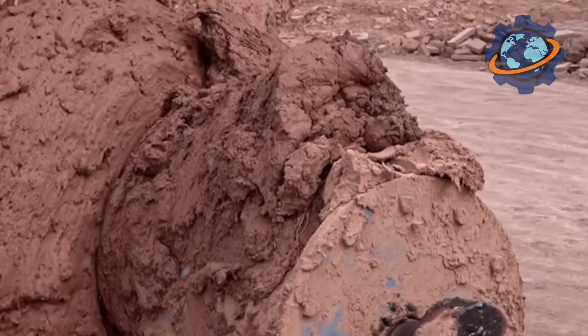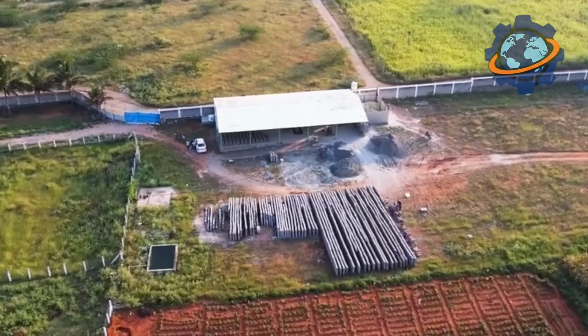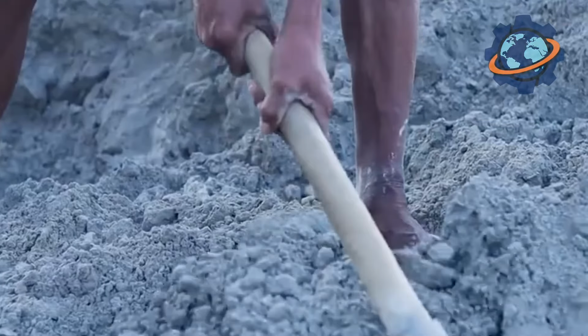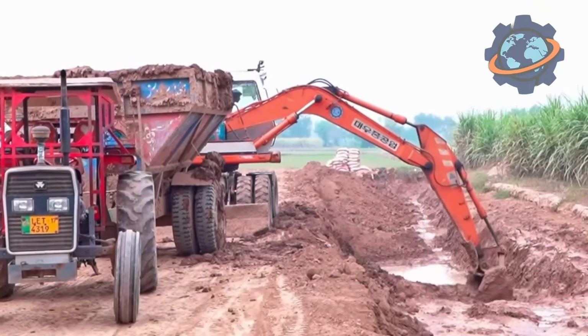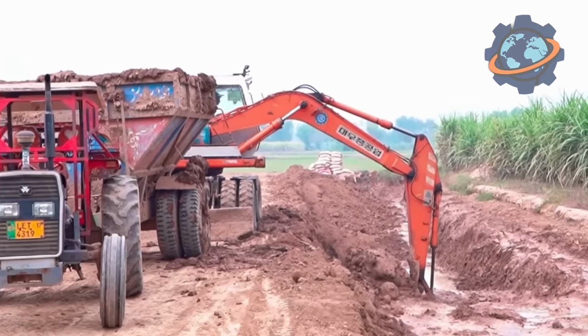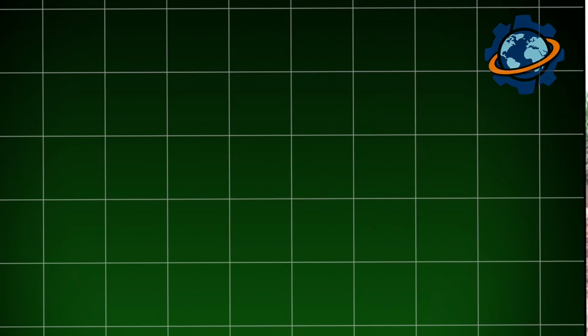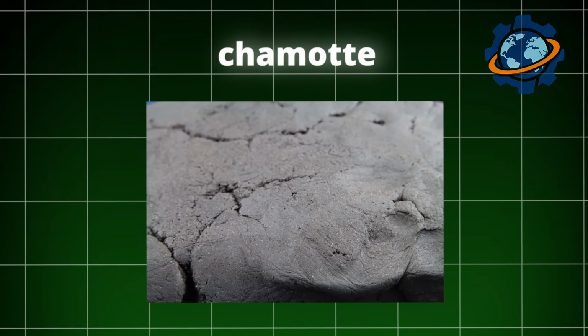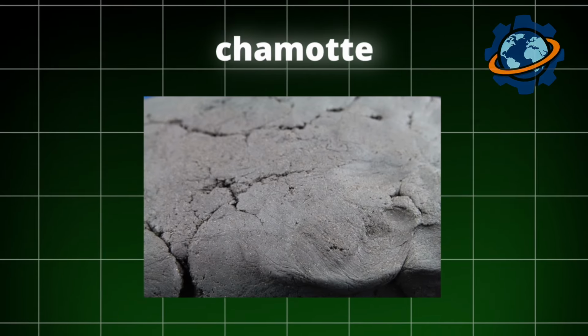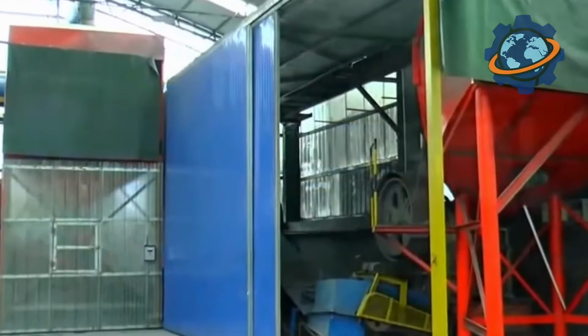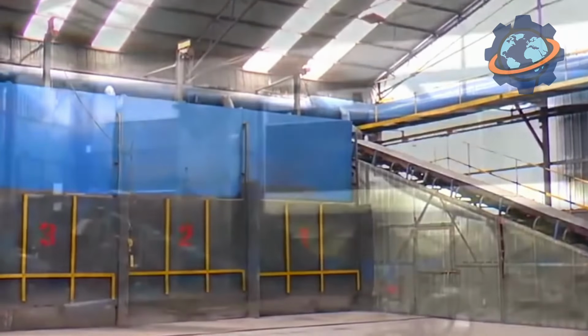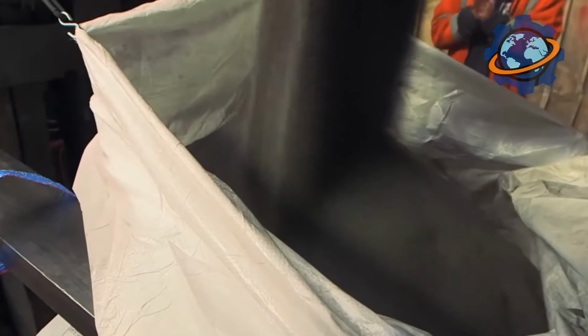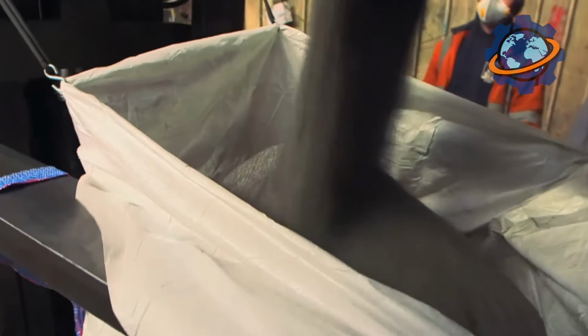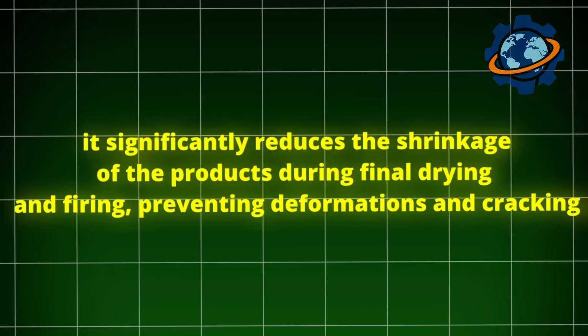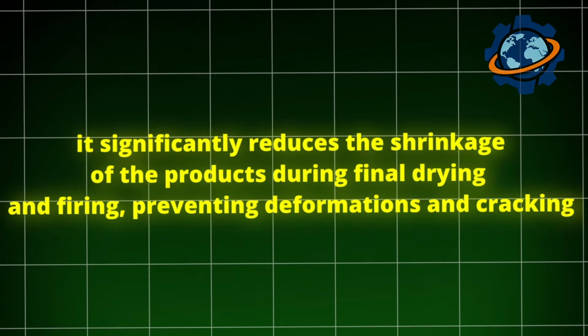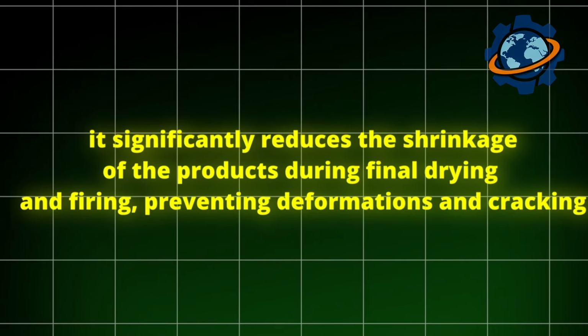Part of the mined clay is not sent directly into production, but is first fired in kilns at temperatures up to 1,500 degrees Celsius. As a result of this process, the clay loses its plasticity, sinters, and turns into a very strong, stone-like material called chamotte. This finished chamotte is then crushed and used as the main component, with a certain amount of fresh, plastic clay added to it, which acts as a binder. This approach solves a key problem. It significantly reduces the shrinkage of the products during final drying and firing, preventing deformations and cracking.